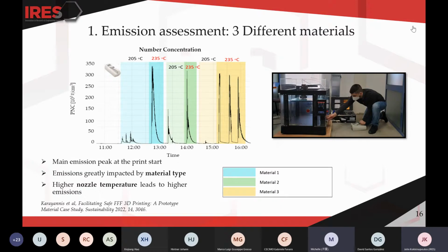The main emission peaks were observed during the print start. Two very important conclusions extracted from this campaign were that emissions are greatly impacted by the material type, firstly, and most importantly, that higher nozzle temperature always leads to higher emissions of ultrafine particles.